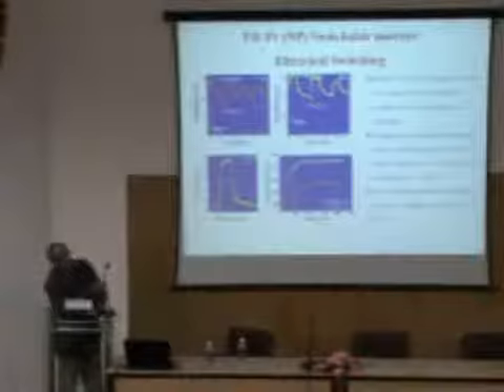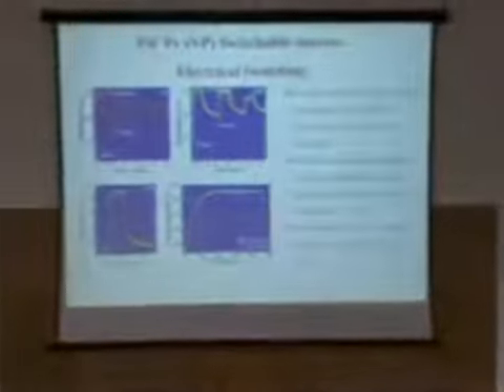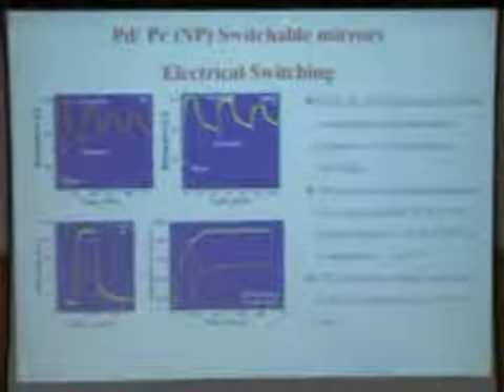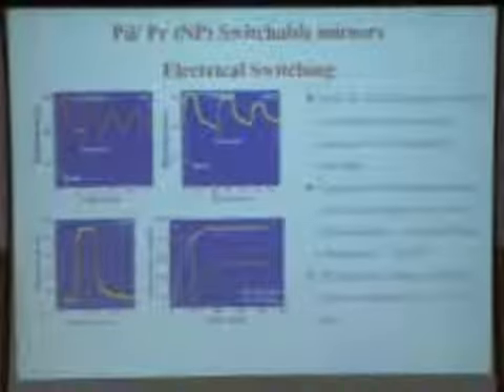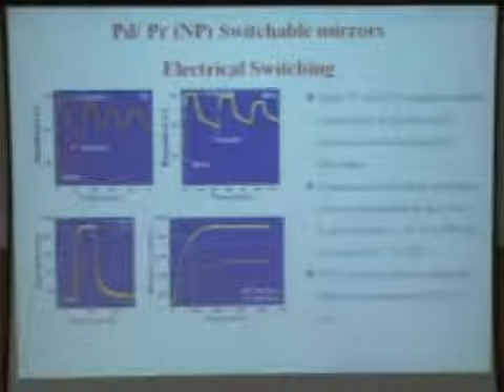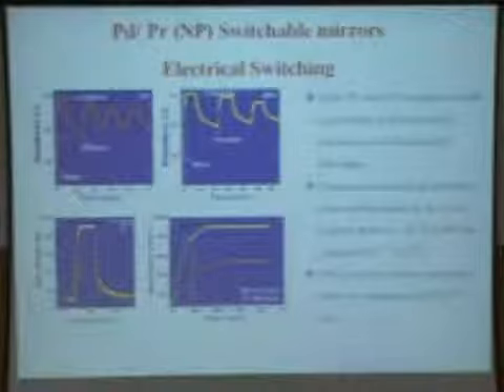This is what I meant: you are in the metallic state. You can see that this is in the case of praseodymium, another kind of rare earth material. There's a metallic state with a certain electrical resistivity. When you expose it to hydrogen, the electrical resistance goes up fast. It goes to a value corresponding to the trihydride. When you remove it from the hydrogen atmosphere, it comes back, and you can see that you're not coming back to this state, but you're somewhere in between. And you can go back and forth.